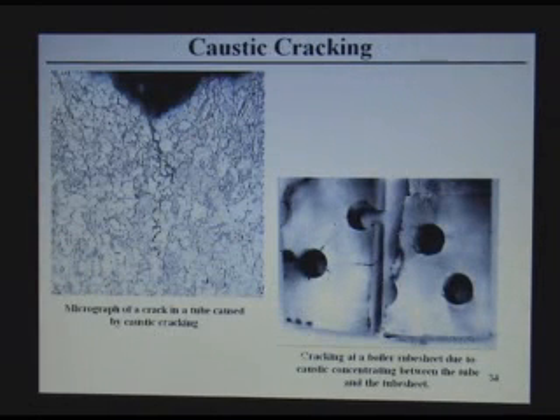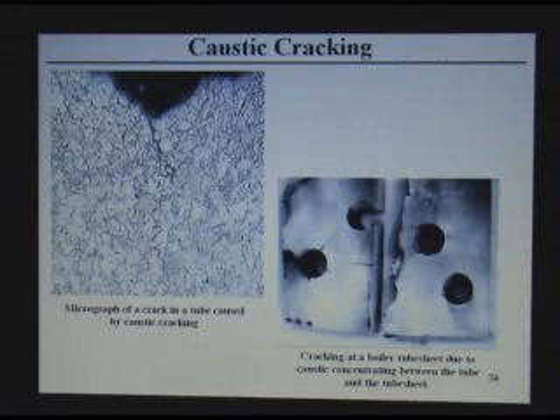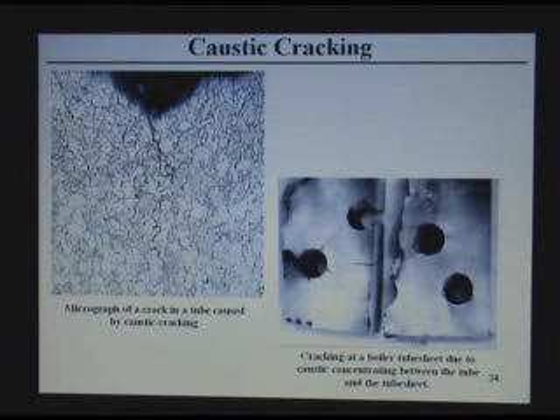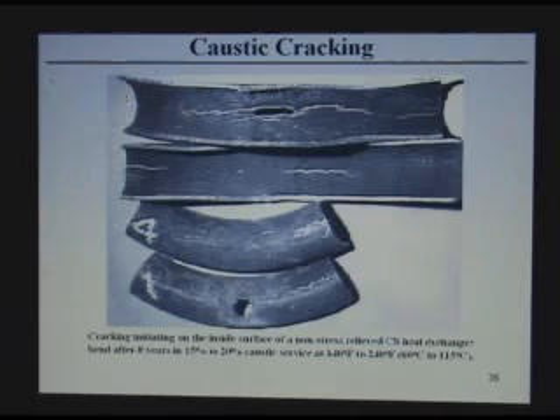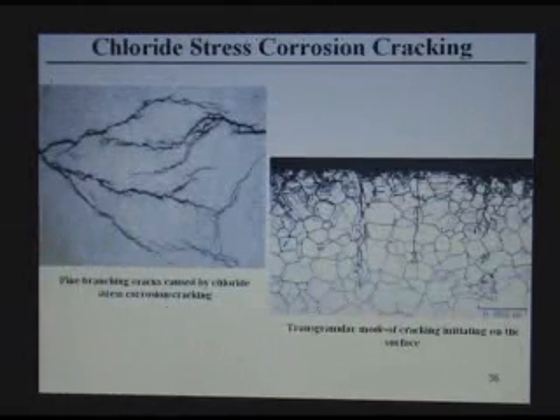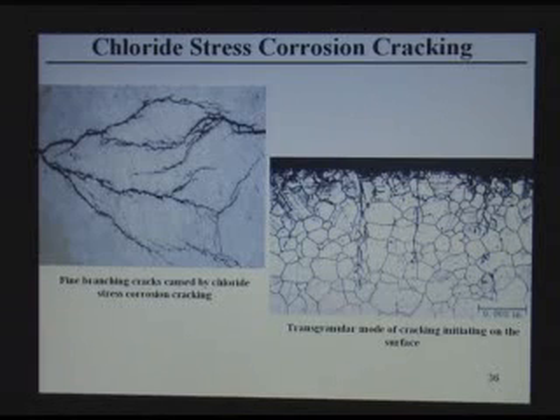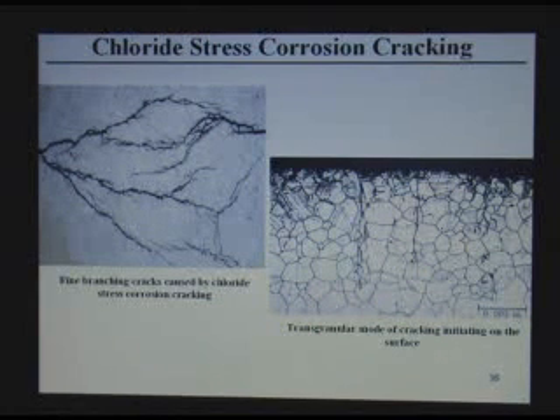This is caustic cracking, it looks like in a boiler or somewhere. You have the tubes rolled in, have high stress, and you have caustic entrapment here, and it cracks carbon steel, as you can see. This is another example of caustic cracking. This is stress corrosion cracking by chlorides, and it is typical. If you see a branched crack like that, it's 100% due to chloride cracking. And you see how it is transgranular.